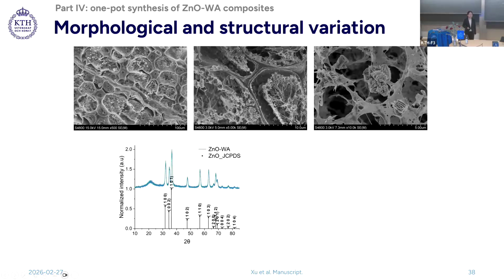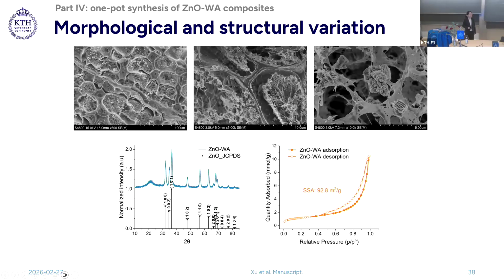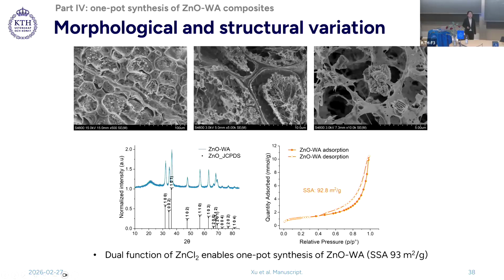XRD analysis confirms the successful synthesis of zinc oxide. Nitrogen adsorption also suggests it is a mesoporous structure with a surface area of 93 square meters per gram. All of this characterization indicates that the dual function of zinc chloride is able to synthesize a zinc oxide wood aerogel composite by a one-pot approach.